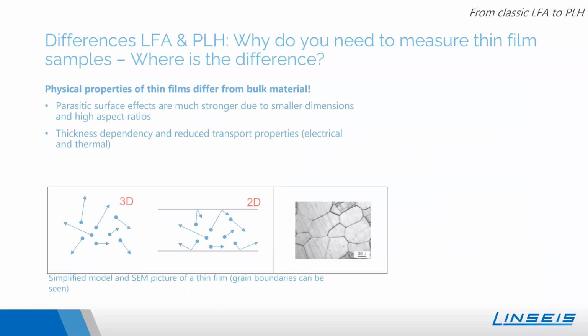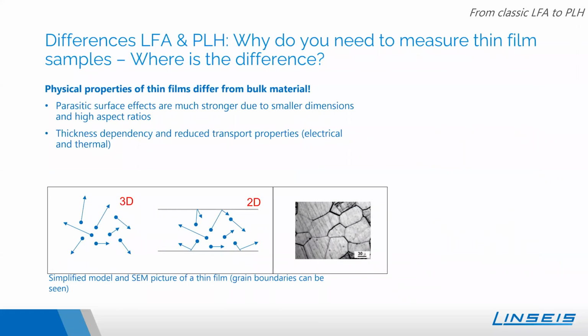But I think now you will ask why we then need to measure thin films instead of just bulk samples. Thin films behave differently. The physical properties of thin films are different from bulk material because of different effects. For instance, the parasitic surface effects are much stronger due to the smaller dimension and higher aspect ratio. That means that the surface plays a much bigger role than the bulk material. And the weight of this influence depends on the thickness of the sample and the volume to surface ratio.